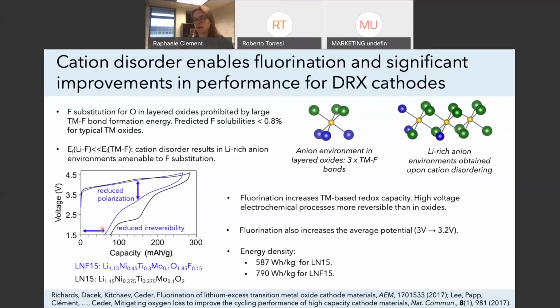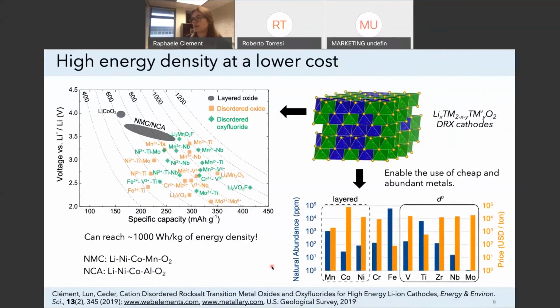Another benefit is that you're increasing the average potential of your cell, of your cathode by substituting with fluorine. And this leads to an energy density that rises from 590 watt-hour per kilogram to 790 watt-hour per kilogram. So this is showing you the performance of these materials, and this is a plot that's showing the voltage of various lithium-ion cathodes, their specific capacity, and if you take the product of these two parameters, you get the energy density, which is shown with these dotted lines here.